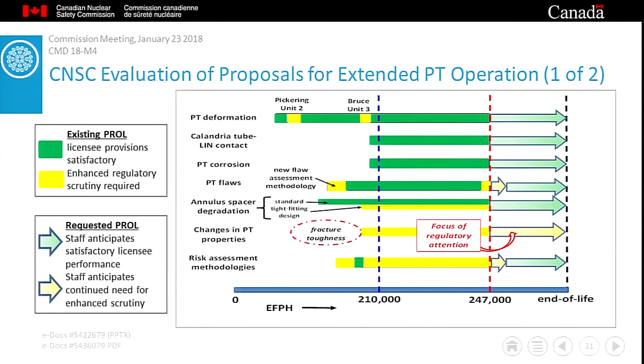For most of the mechanisms, a green bar is shown, both in the lead up to the units crossing the 210,000 EFPH hash mark, which is shown in blue, and their approach to 247,000 EFPH, a hash mark shown in red. This confirms that for each of those degradation mechanisms, staff has carefully reviewed licensee provisions to manage the associated risk and has met all applicable acceptance criteria. The lighter green bars, which extend beyond 247,000 EFPH, indicate that while staff will continue monitoring licensee performance on each and every one of those degradation types, we do not anticipate a change in the outcome.